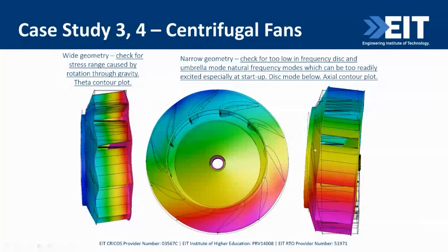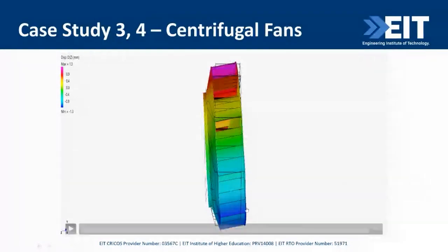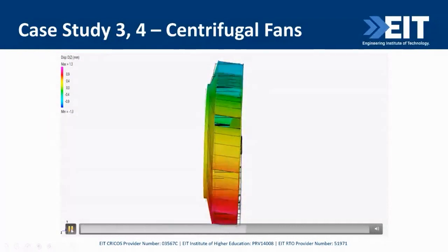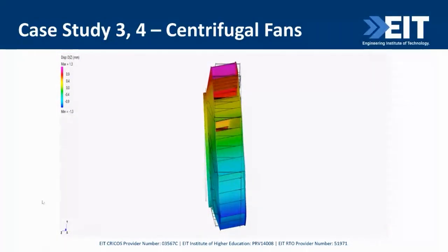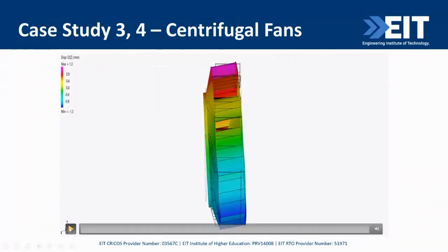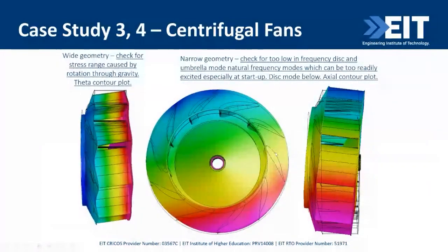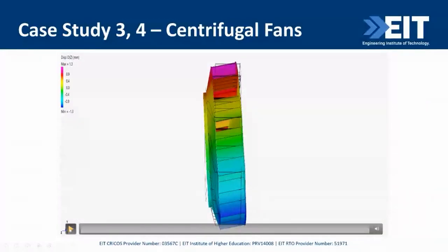And here you've got a narrow impeller, with the first disk mode being excited, and that's an axial contour plot, and it shows that disk mode with the node line of the motion halfway across the impeller. The other main disk mode, the lower main disk mode, is the umbrella mode, where the whole impeller fluctuates like an umbrella, opening and closing. Obviously very small displacements, but those need to be not excited as you start up and run down, and for narrow impellers they can be a problem.